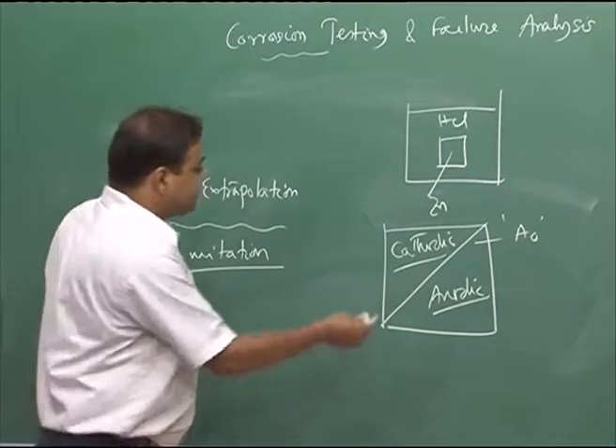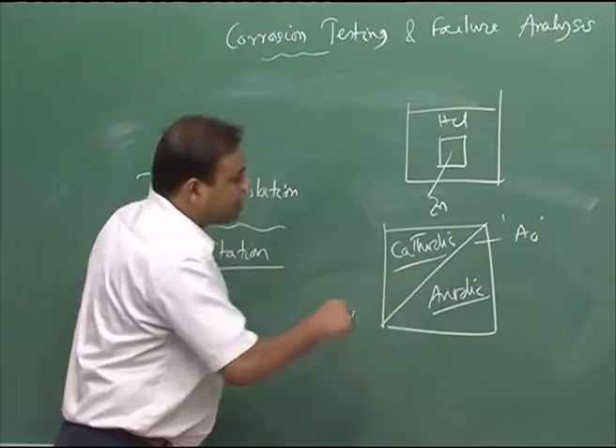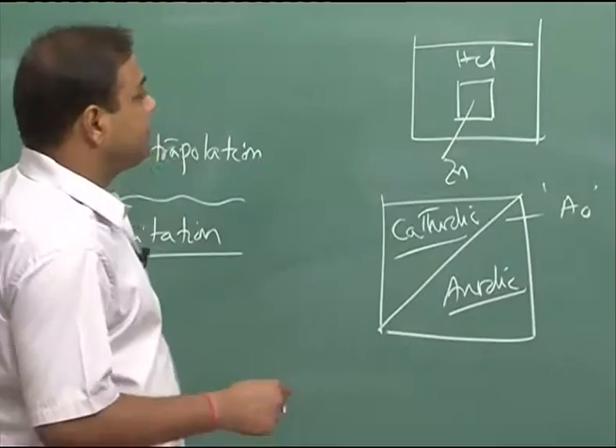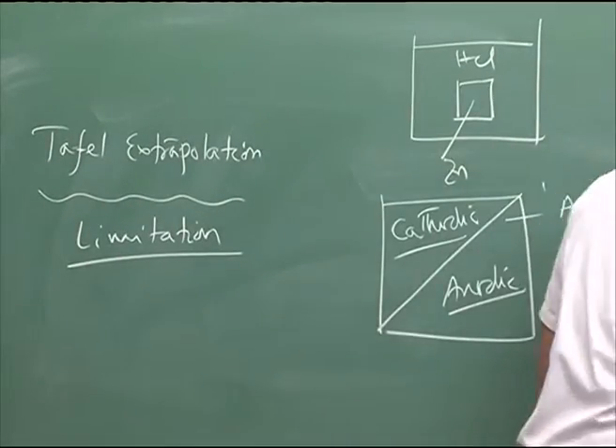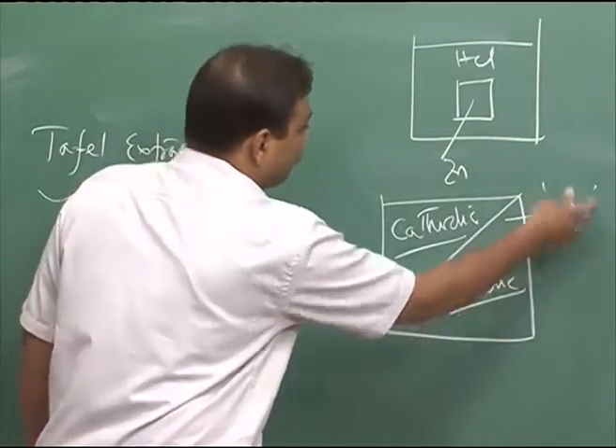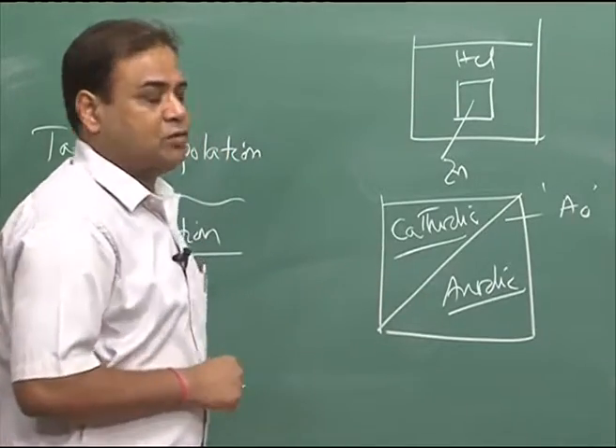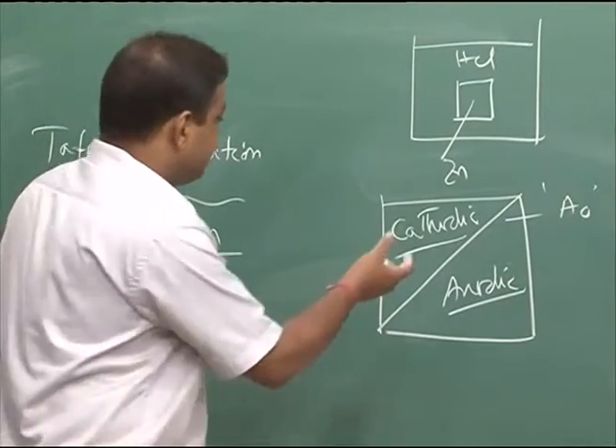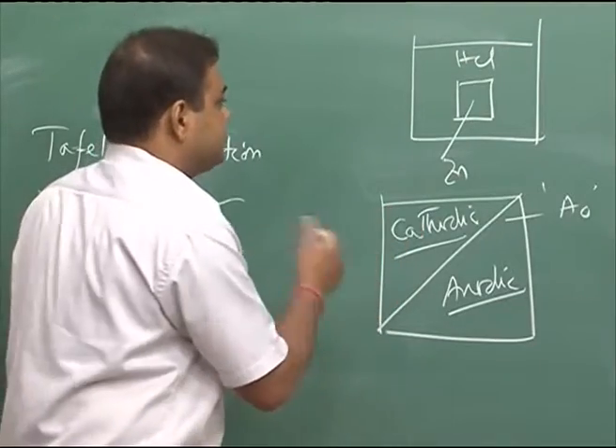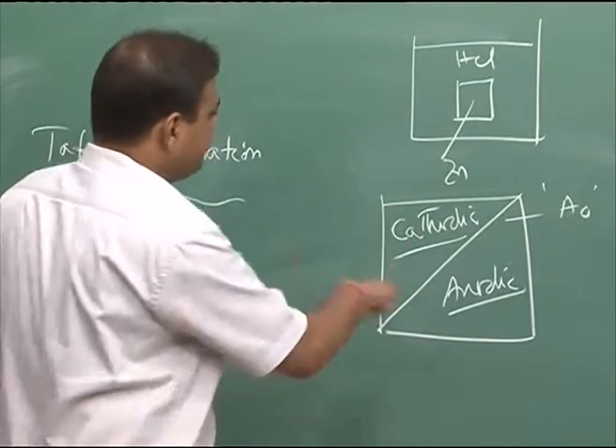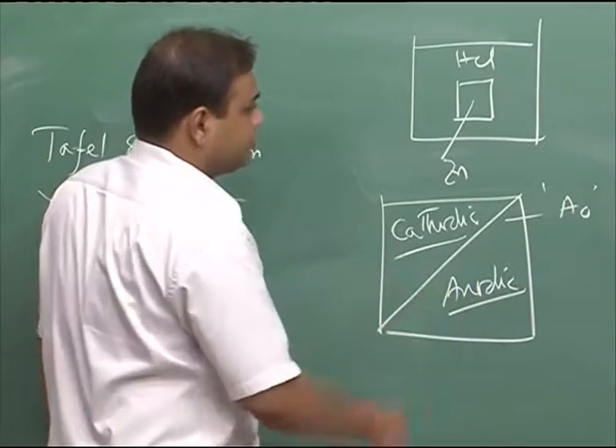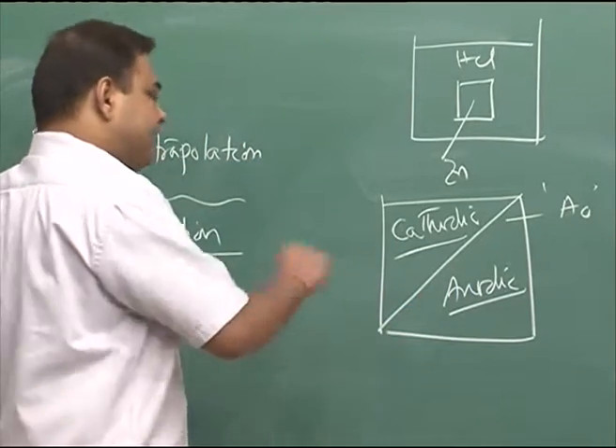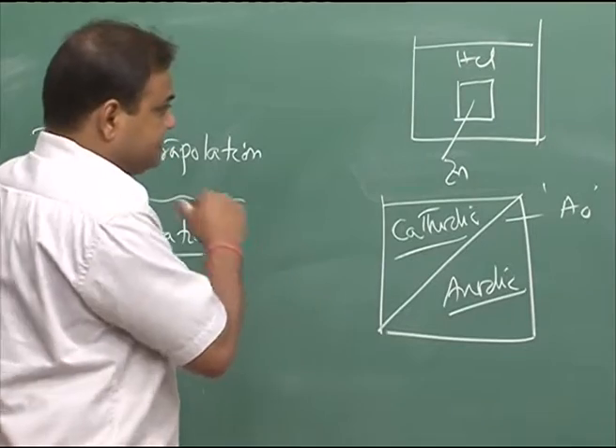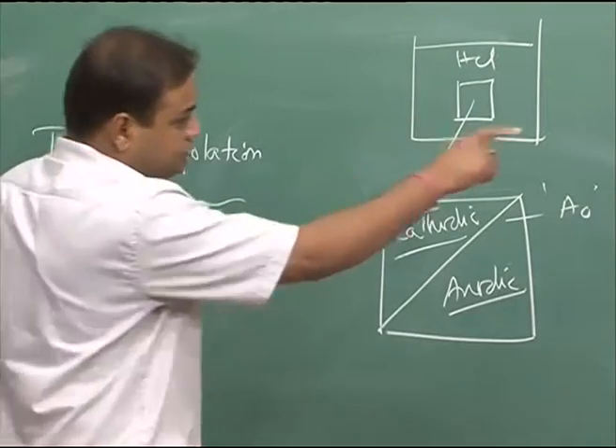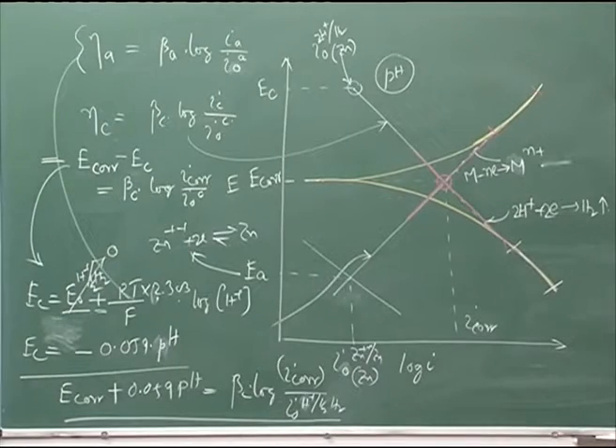So actually the corrosion rate is half of what we are measuring from this route, because there the assumption is that the whole area is active as anode. So we are getting double the corrosion rate than the actual. This would happen depending on the area ratio of cathodic and anodic regions, giving less corrosion rate. The practical rate would be less compared to the theoretical experimental rate found from Tafel extrapolation.